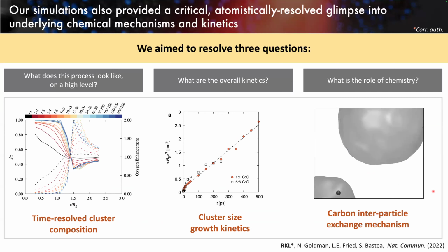In fact, what I'm showing here, this little black dot is a carbon atom. This is a small carbon nanoparticle. This is a big one. What we're doing is watching this carbon atom move from one cluster to the other. While this carbon atom moves, we're rendering in red any oxygen atoms that are within bonding distance of that carbon atom. What we find is anytime that particle is at the surface or outside of a particle, it's always existing in a state where it's forming carbon monoxide or carbon dioxide. So in essence, we have a reaction-mediated transport mechanism.